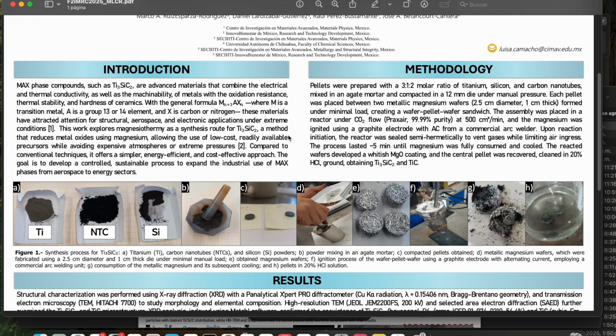The processing sequence emphasizes controllable ignition, rapid reaction, and straightforward post-treatment. Ignition was done with a graphite electrode using an AC arc welder. The reaction ran for about 5 minutes until Mg was consumed, and the pellet was then recovered and leached in 20% HCl to remove MgO and other soluble byproducts. This sequence was chosen to privilege speed, reproducibility, and compatibility with readily available hardware.